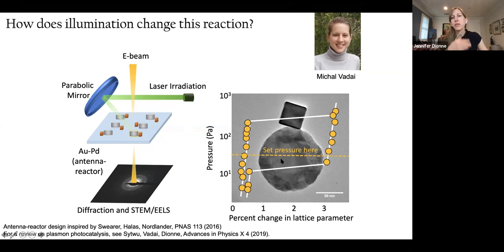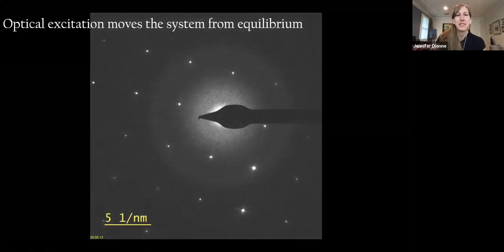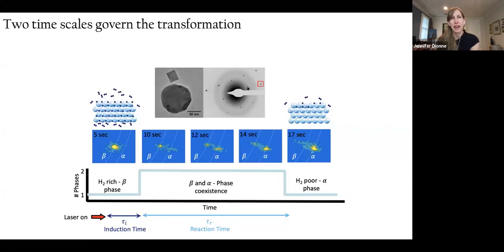And for this particular antenna reactor pair, we can again look at the equilibrium thermodynamics. What we're going to do is look at dehydrogenation. So we'll set the pressure just above the unloading pressure, and without any illumination, the system will stay in equilibrium. We optimize the electron beam conditions such that it does not perturb the system from equilibrium within a reasonable time frame for the experiment. It's only the light that's going to be pushing the system out of equilibrium. And here's an image of the diffraction pattern. We've turned the light onto that antenna reactor pair. You can see for a while nothing happens, but then after a few seconds, the diffraction pattern actually expanded, corresponding to the transition from the beta phase to the alpha phase.